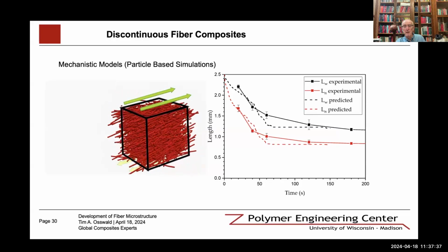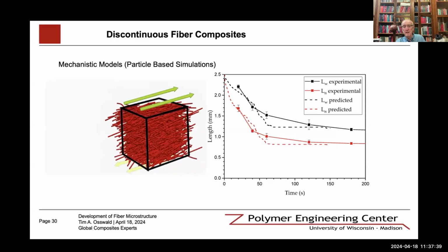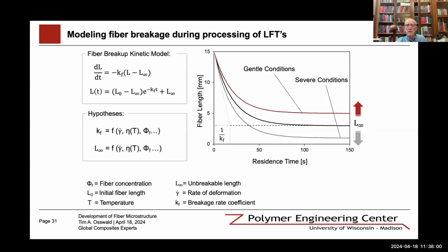So we compared that to the Couette experiment. So you can kind of see over time how the system broke the fibers down. Basically, we start out with a higher fiber length, and eventually we reach an equilibrium fiber length, or an unbreakable length. And so based on that, we build on a first order